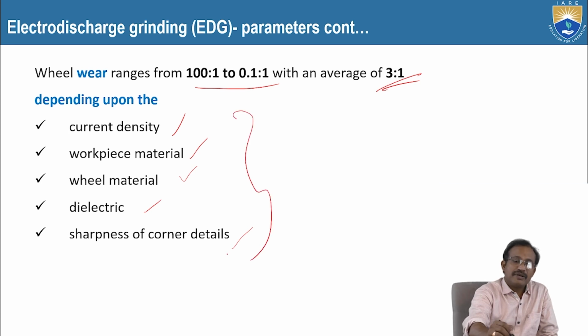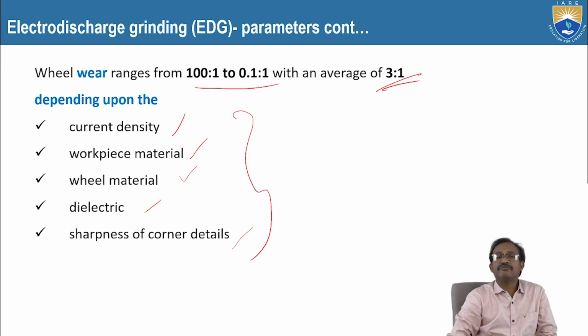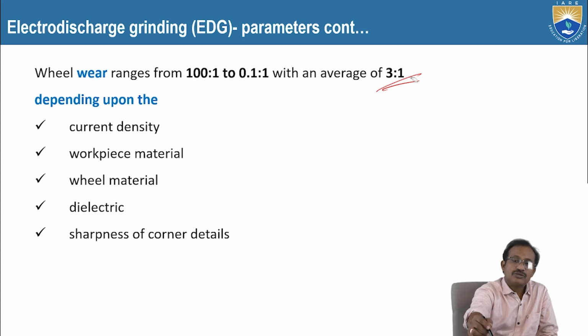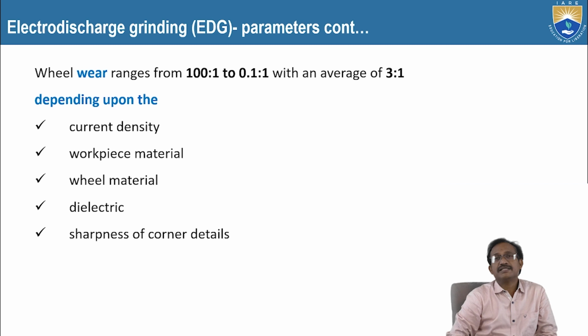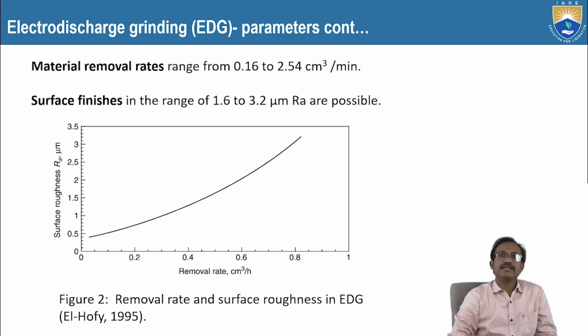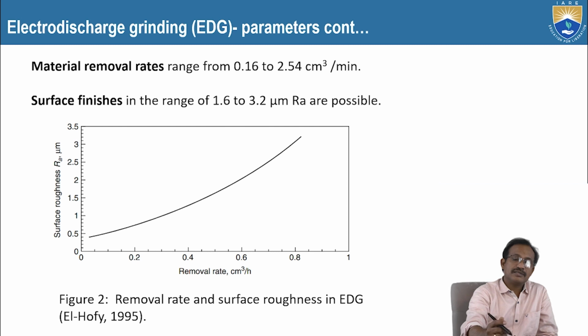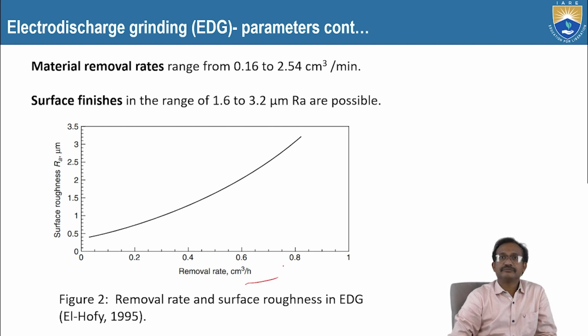So these parameters influence the wear characteristics of the rotating tool and the workpiece. Obviously we need to remove the material from the workpiece, but at the same time the tool will also be subject to some wear. Now look at this graph. On the x-axis, removal rate in cubic centimeters per hour. On the y-axis, surface roughness in microns, Ra. Here the relation between these two is not a straight line.